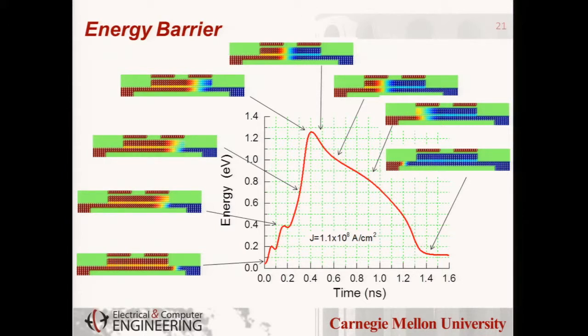You want this, and there's an energy barrier between these two states. One on this side and one on the other side, this domain wall. As this domain enters the free layer, the domain wall area increases and the energy rises. After you pass through this device, the energy falls. Here's the energy barrier. In this specific case it's more than 1.2 electron volt, more than 40-50 kT for room temperature.